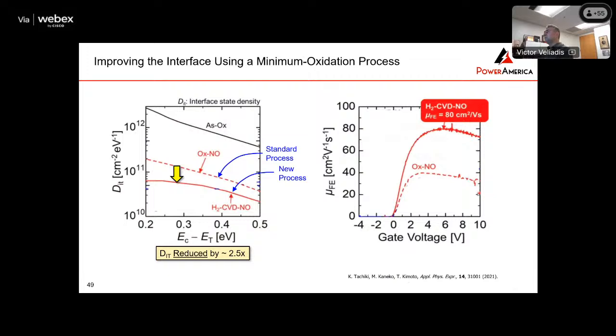And also, if you look at the mobility, this is the mobility of the standard oxide process, and this is the mobility of the electrons. When you use this improved process, you increase the mobility by 2 times. So that's a very promising result that is at the experimental stage at this point.